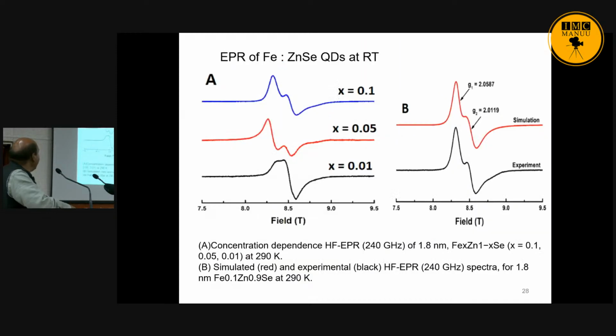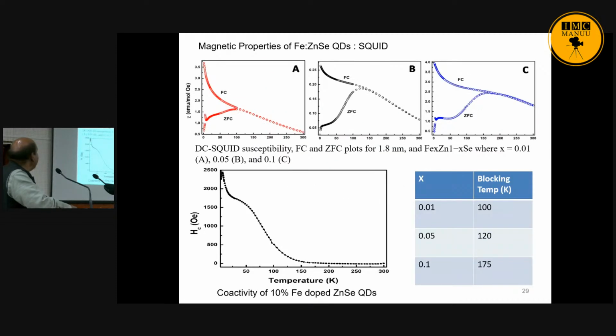Then we did the EPR. With the help of EPR, we are able to confirm that iron 3 is doping in the ZnSe quantum dot. And after this, we take magnetic measurements. This is the DC susceptibility, the ZFC, the zero field cool and field cool. Then you can get it here.